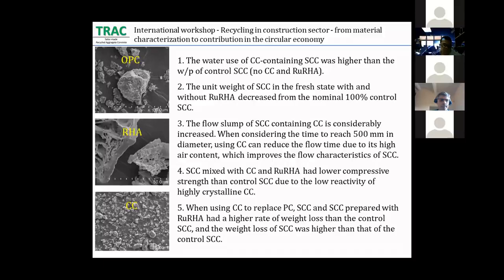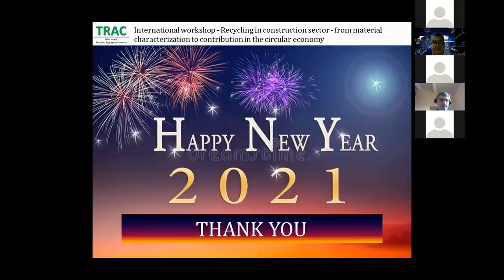Five, when using calcium carbonate to replace Portland cement, self-compacting concrete prepared with rice husk ash has a higher rate of weight loss than the controlled self-compacting concrete, and the weight loss of self-compacting concrete was higher than that of the controlled self-compacting concrete. Thank you and have